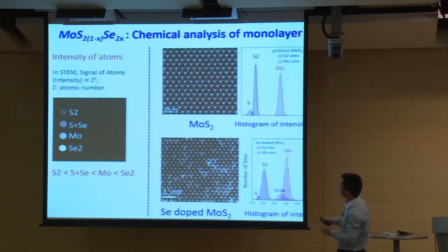And if we can do some statistics for all the intensity, we get the histogram of this intensity, which here, this is the intensity of moly, and this is the intensity of 2 sulfur. And we have some areas that have 1 sulfur defect, so we can get a very small peak here.